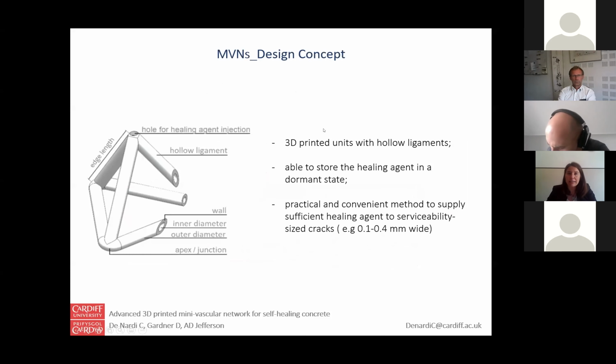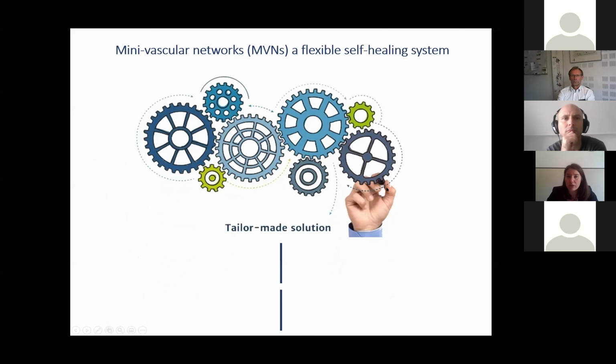So we are proposing an alternative approach, which is the use of mini-vascular networks. Basically, a mini-vascular network is a 3D printed hollow unit where the healing agent may be stored inside. So basically, the healing agent or the glue can be stored inside the vascular network. It remains dormant until a crack crosses one or more ligaments, breaks them, and then releases the healing agents, and thereby heals the crack. So it is a practical and convenient method to supply the healing agents to a serviceability-sized crack in a range of 0.1 to 0.4 millimeters.